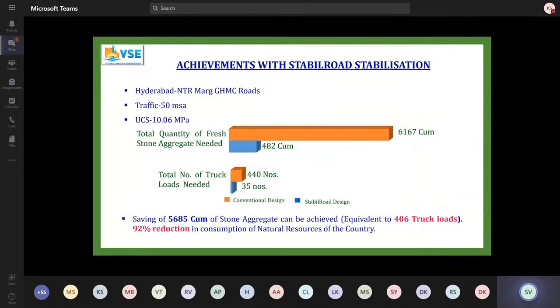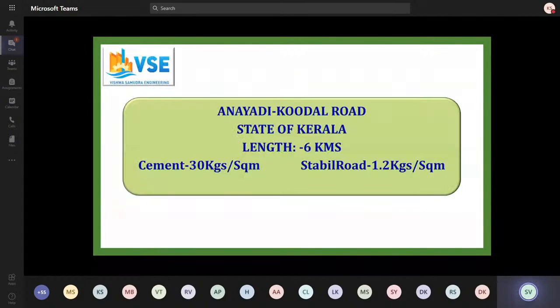Again, on the Hyderabad roads we saved around 92%. This is a road we did in Kerala. If you remember, there were some very bad floods about 2 years ago. They asked us to come and do one stretch which was badly damaged. Here we used about 30 kgs of cement and 1.2 kgs of additive. This was how it looked. Almost the entire road was full of potholes.